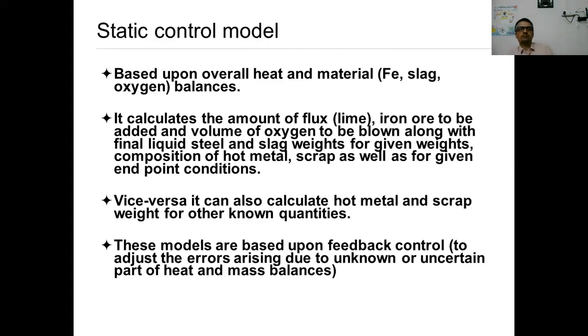So what is a static control model? It is based upon overall heat and material balance. If I'm talking about the material balance, then it involves the Fe balance, slag balance, and oxygen balance. It calculates the amount of slag-forming materials like lime, iron ore to be added, and the volume of oxygen to be blown, along with final liquid steel and slag weights, for the given weights and composition of hot metal and scrap, as well as for the given endpoint conditions. Vice versa, it can also calculate the hot metal and scrap weight for other known quantities.